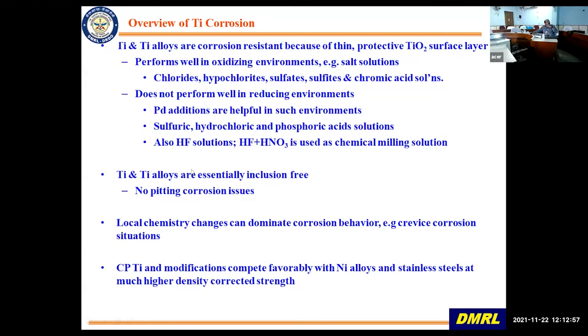Then titanium and titanium alloys is slightly different as compared to steel. Because it is melted in vacuum and the materials are very pure, there are no inclusions. So there is no pitting corrosion that happens. But the local chemistry changes can dominate the corrosion behavior, and you can have crevice corrosion. I will just briefly show you that.